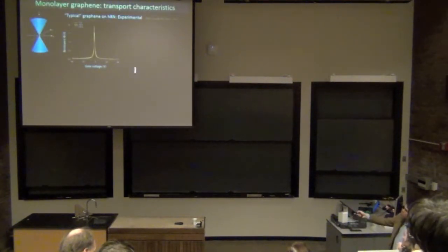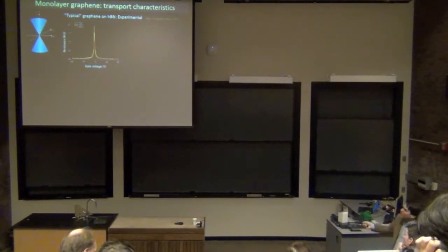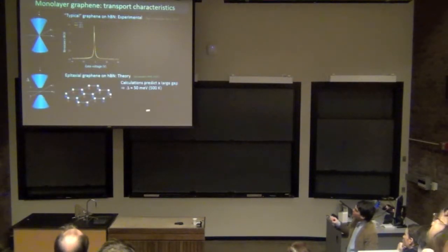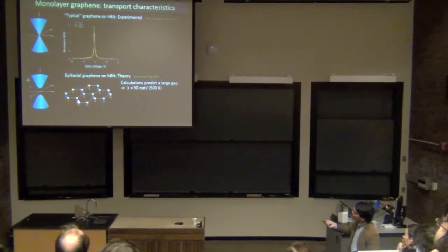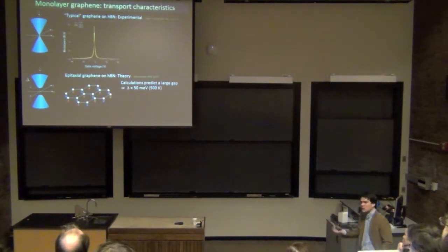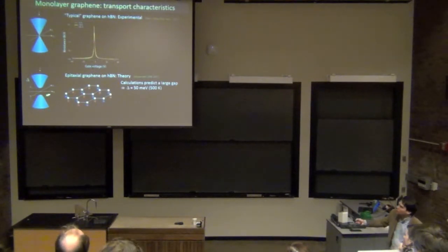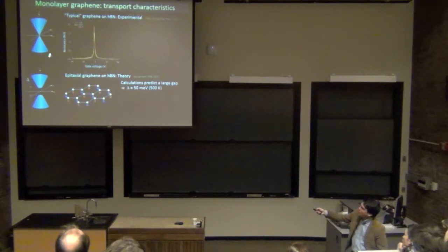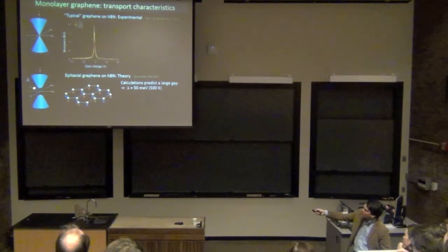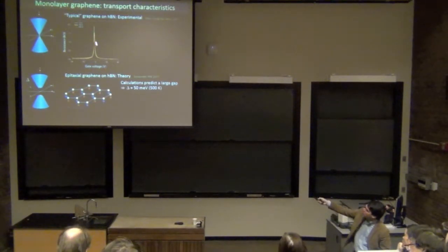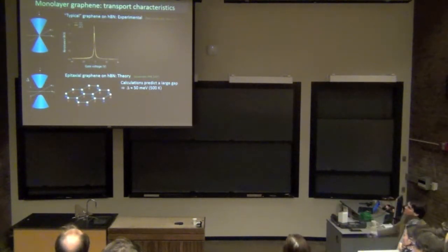And as I just showed you, there's this resistance peak in a graphene device as a function of a gate voltage. It's a little bit surprising because, even before this was measured for the first time, it was predicted from theory that if you had a structure in which graphene was sitting on top of boron nitride in this manner, the graphene would somehow inherit some of the properties from the boron nitride and actually open up a gap in the same way that boron nitride has a gap. And the conduction here would actually be much, much, much lower than represented by that peak.